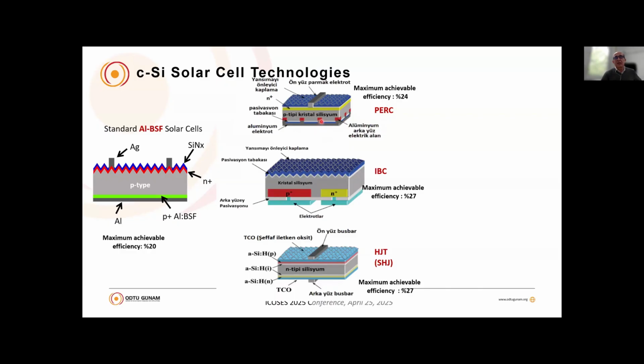Instead, there are some local touches here, some local contact between aluminum and the silicon substrate. The other regions are covered with passivating material like aluminum oxide or silicon nitride. So this local contact structure on the backside has improved efficiency enormously. We have seen efficiency values around 24% by using these PERC cells.